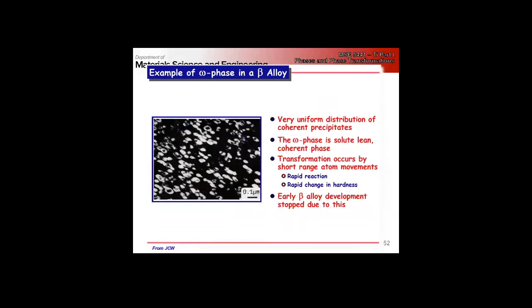Omega phase, on the other hand, this transformation is short range atomic movements. Remember, we looked at those animations. That was collapse of the BCC to omega by the shifting, right? We had A, B, C layers. The A and the B and the C layers, those atoms collapsed onto one to give us the simple hexagonal from the BCC. So this is a fairly rapid reaction, happens nearly athermally, and then you have diffusion out, right?